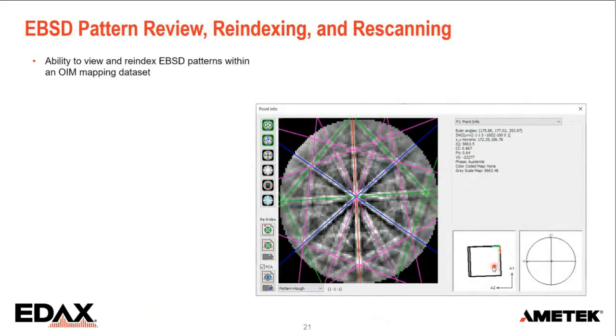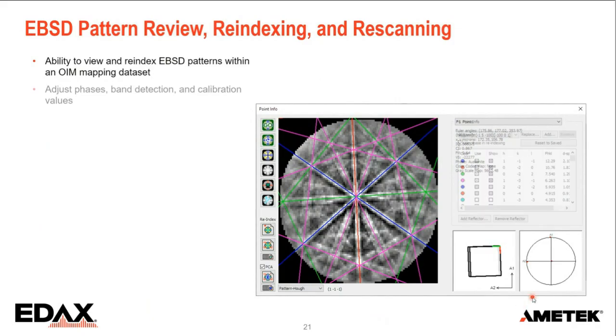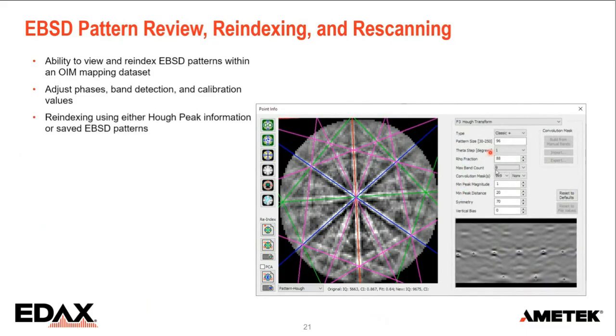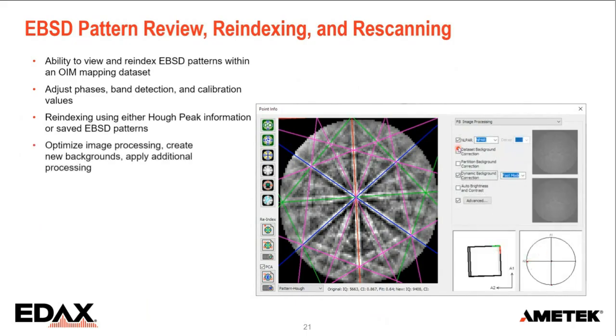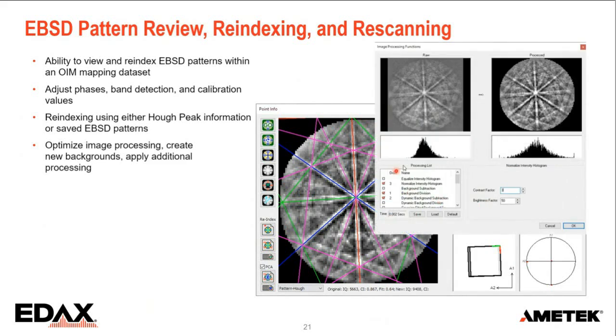And just to illustrate that view, here we can pull out this window. You can adjust phases. You can say use this phase or not. You can change the reflector table if you want to. You can modify the band detection with all the parameters that we have available for the Hough transform. You can do the image processing. You can switch on NPAR. You can do all kinds of other image processing, even advanced. You can make your own recipe of how you want to process patterns to really maximize the band detection. And then you can index by point, by subset, complete data set, any way you like.